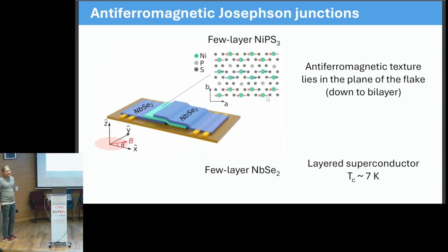So that's how we got in contact with these people in Constance when we were discussing different materials. They had this material, they have a glove box, so my student went there and prepared these devices. And the devices essentially are like a sandwich, right? We use niobium diselenide as superconductors, and we sandwich one layer of this NiPS₃ between two niobium diselenide layers. And we studied, are we getting to topology? Okay, that's not the point. We wanted to see what emerges from the interplay of the superconductivity and this antiferromagnetic texture.